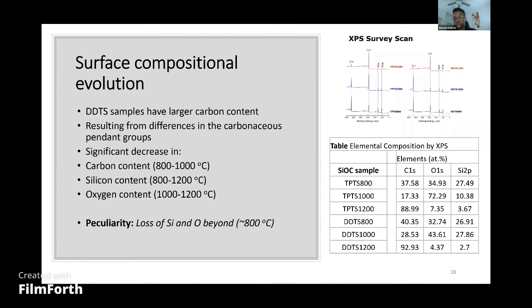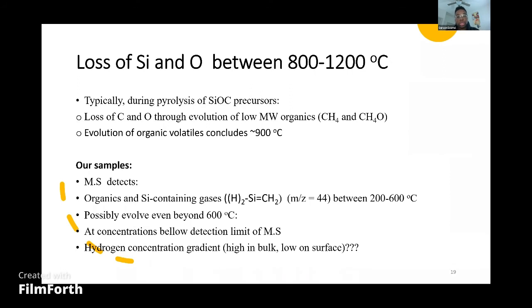Typically, during the pyrolysis of polymeric precursors for silicon oxycarbides, we tend to not see significant loss of silicon and oxygen at temperatures beyond around 800 to 900 degrees centigrade. Typically, these tend to be pretty constant all the way to around 1200 to 1400 C, when they begin to undergo carbothermal reduction. So the significant loss of silicon, more precisely, at temperatures even close to 1000 degrees centigrade, makes these polymeric precursors rather peculiar. In this case, the loss of silicon and oxygen between 800 and 1200 degrees centigrade can be indicative of silicon and oxygen leaving the sample at temperatures between 800 and 1200 degrees centigrade, either as organometallics or even as organics.